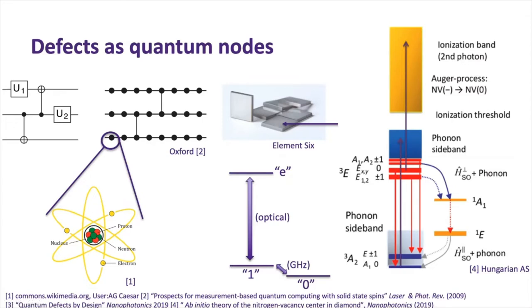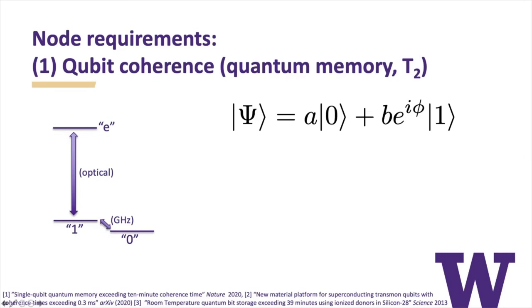Okay. So once we've isolated this type of atomic qubit structure with this optical transition for network applications, we can ask, what do the properties of this defect need to have? And one of them is that it has a long qubit coherence. We represent the qubit state as this coherent superposition between 0 and 1. And what that means is that there's an amplitude and a relative phase between these two. And the lifetime of the amplitude and phase determines how long you can store the information.